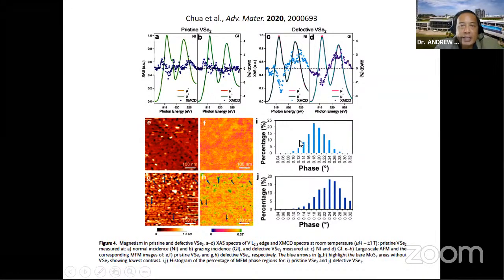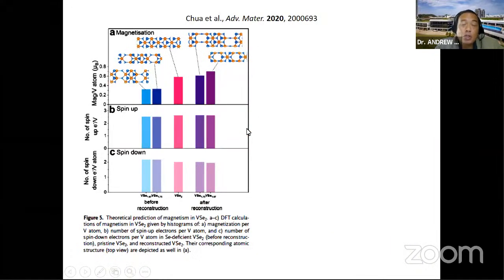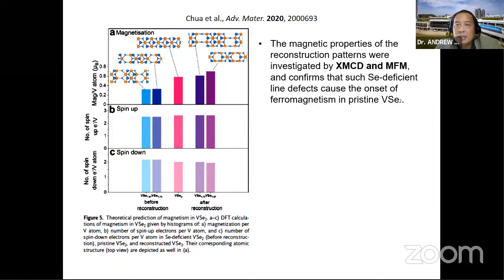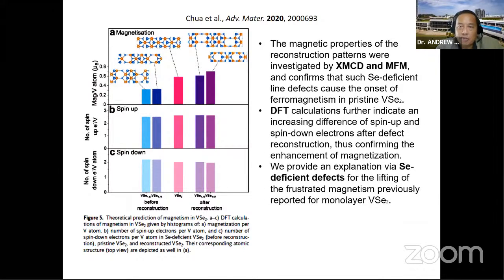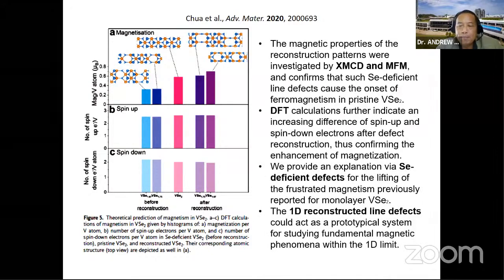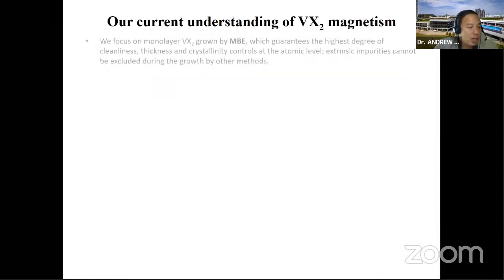And here are the data of the phase changes in these two sets of images. So we have shown that defects, and of course we have done calculations that show that before the reconstruction and after the reconstruction, you can see a net increase in magnetism. So our conclusions are that selenium-deficient line defects can cause ferromagnetism in pristine vanadium diselenide, and DFT calculations confirm this. And we hypothesized that some of the papers published prior to this that showed magnetism could be due to defects in the materials.